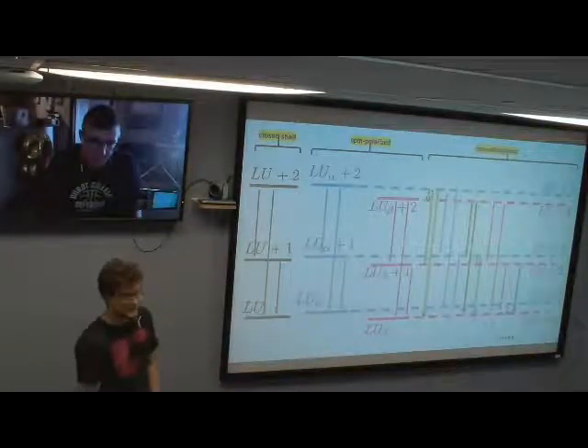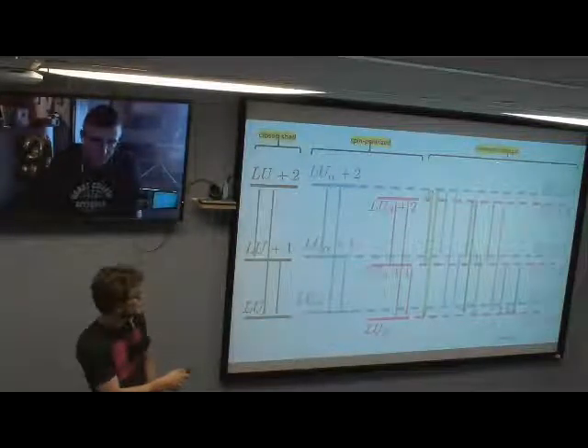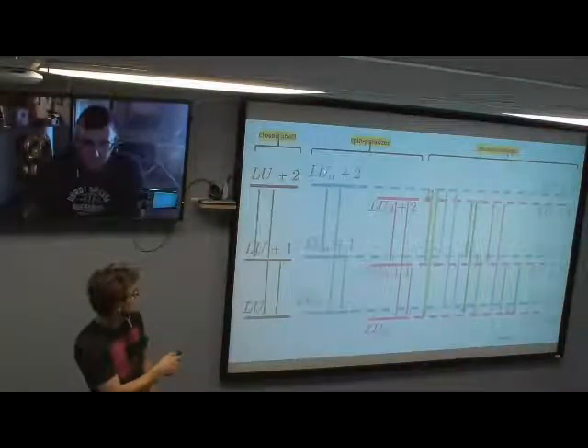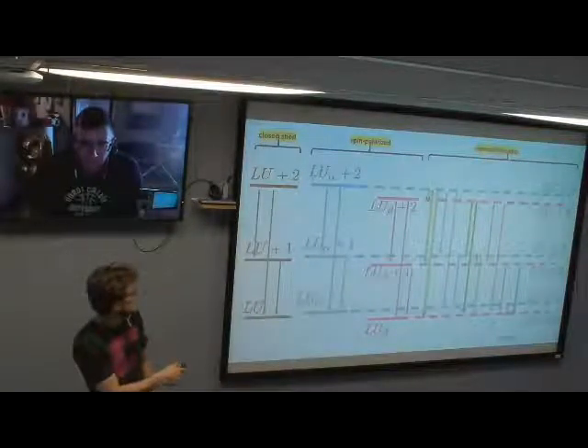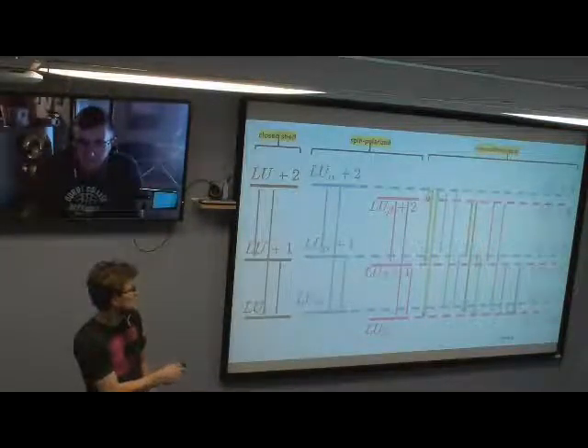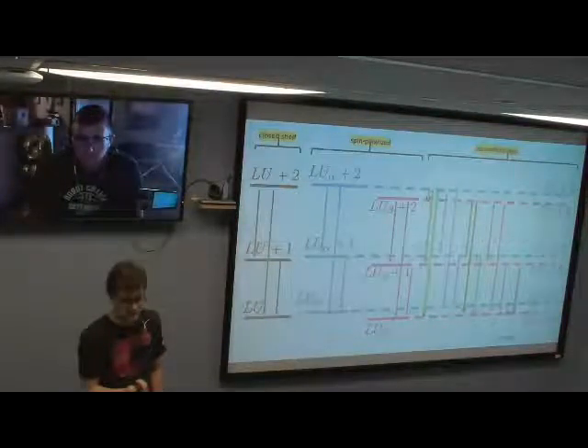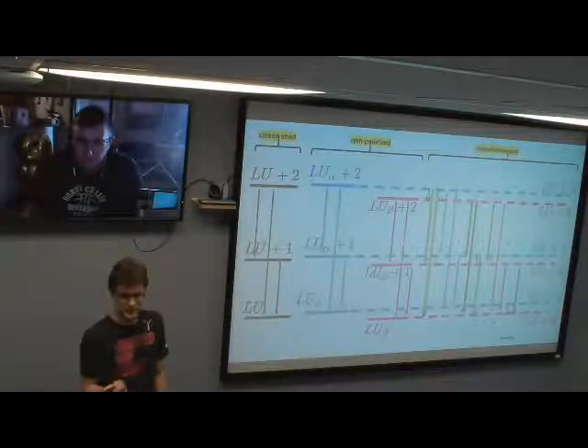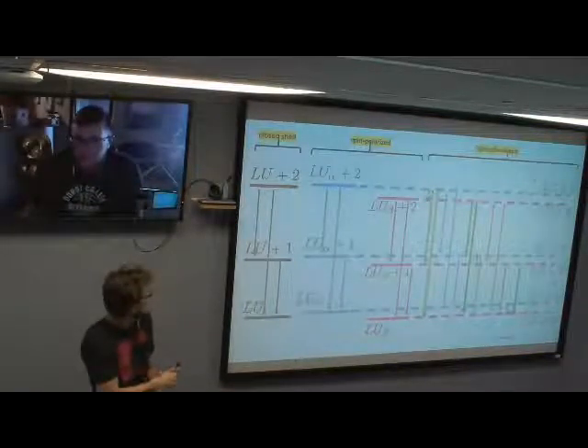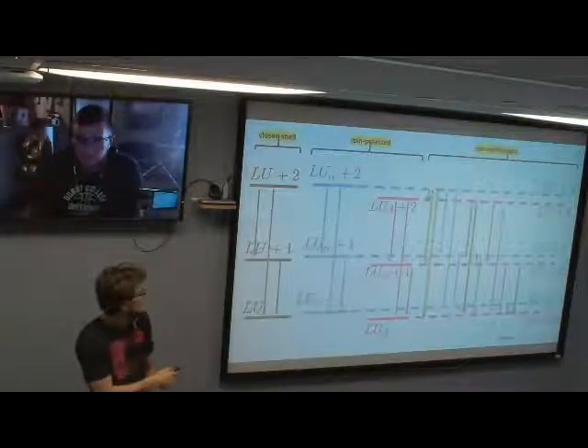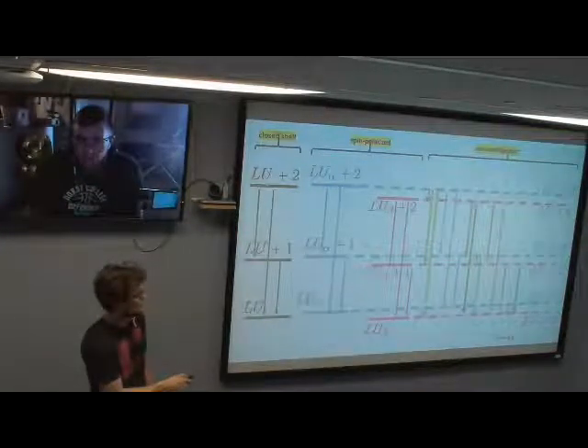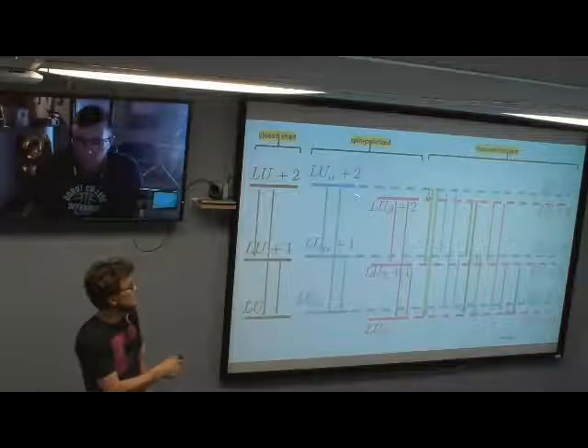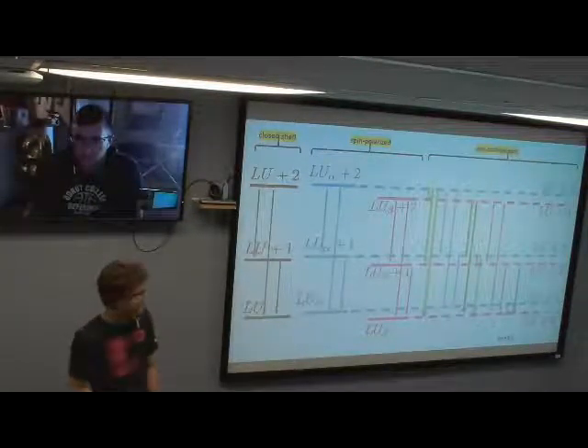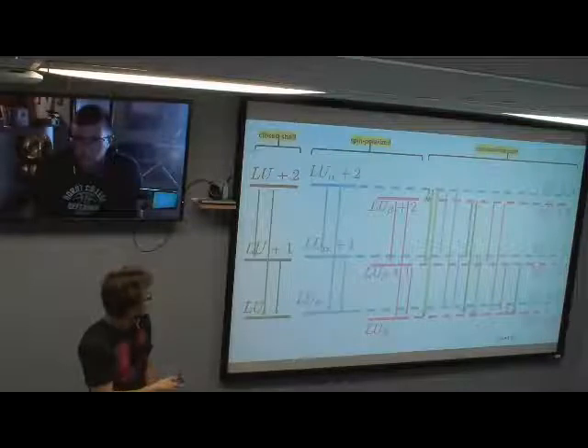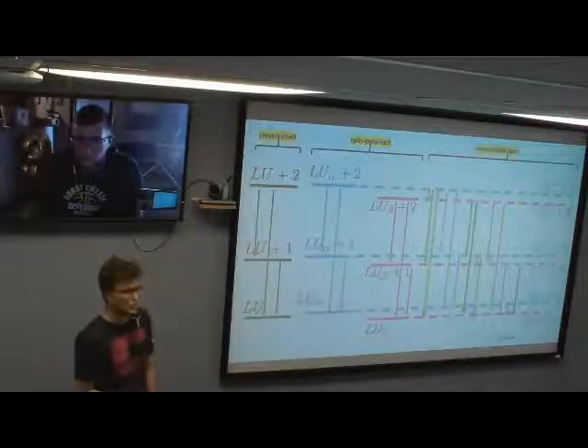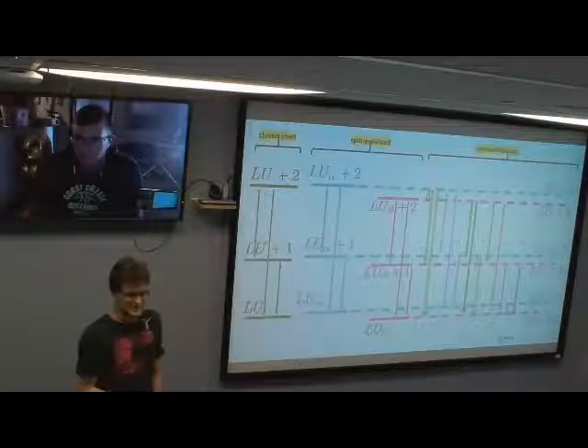What we included for excited state dynamics is that you can go to non-collinear spin calculations. In a lot of situations, your LUMO alpha and LUMO beta states aren't going to change in energy that much when you include non-collinear spin. If you include spin-orbit coupling, it'll affect them a little bit. But with non-collinear spin, they're not going to change, but you can get additional pathways for transition. So you could have a LUMO+5 to LUMO+4 transition in a situation where you wouldn't be able to get that in a spin polarized calculation. The take-home message is you just have a lot more work to do when you do non-collinear calculations.